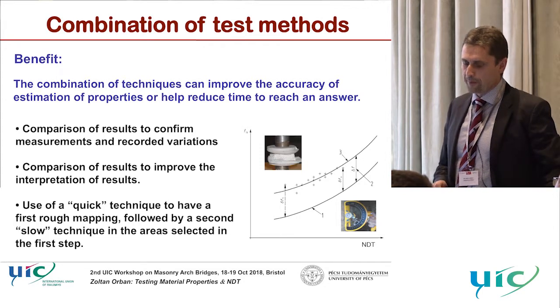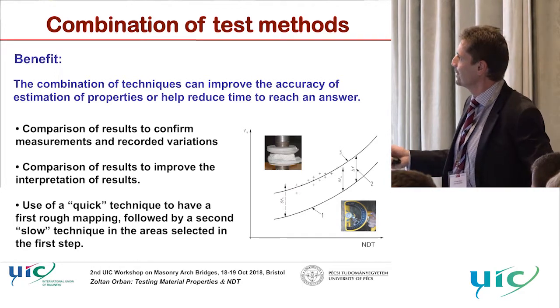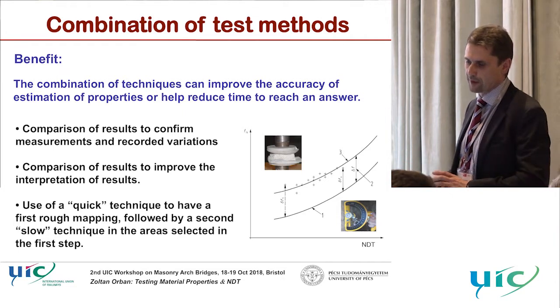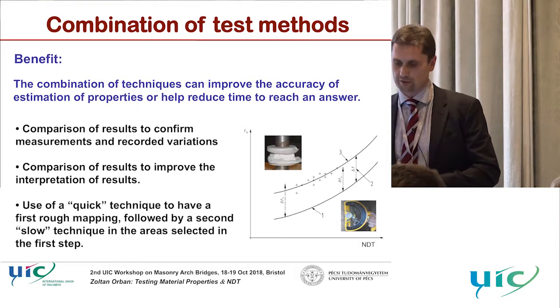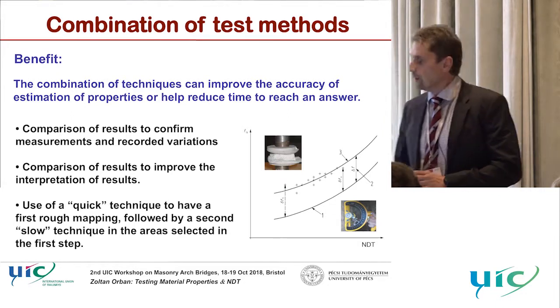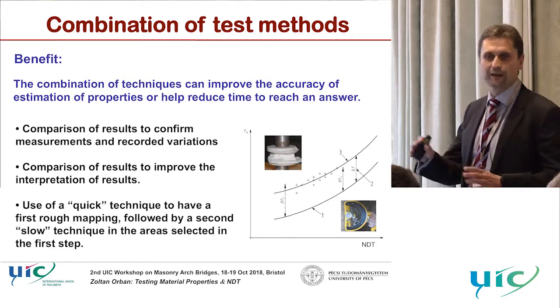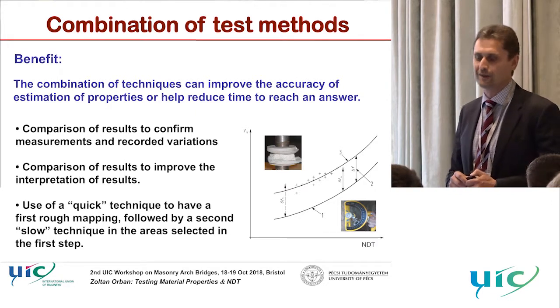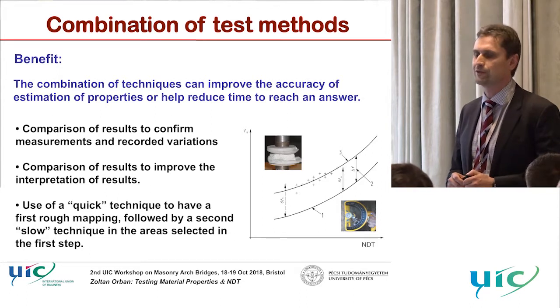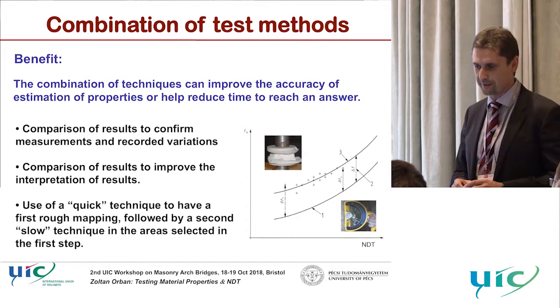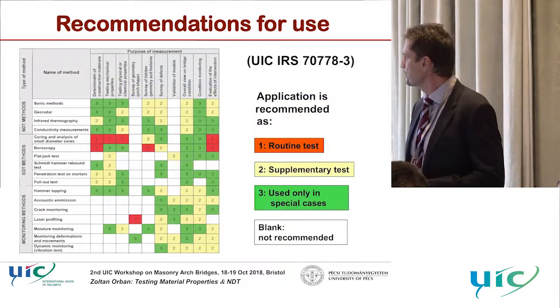I have already referred to the benefits of combining test methods. The combination can be used to compare results, confirm measurements, and improve interpretation. A third approach is to use a quick and relatively cheap technique to make a rough first mapping of condition, followed by a more detailed slow technique on selected areas. This is the recommended way to test arches — start with an affordable reliable method before applying more expensive sophisticated techniques.